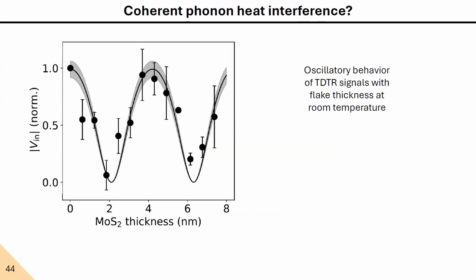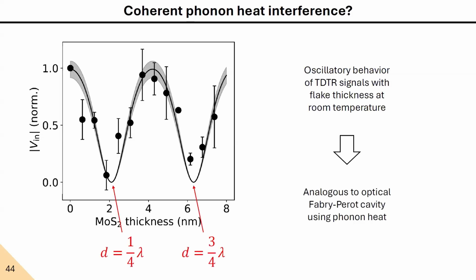If we plot the signal magnitude normalized to the substrate value for all our measurements, these are averages of multiple measurements and samples, so that we can cover the entire thickness range, we see this oscillatory behavior. And this is an experiment that is analogous to an optical Fabry-Perot cavity. But in this case, we're using phonon heat as our observable. And these specific resonances, where we see no signal, would correspond to 1/4 and 3/4 wavelengths of the phonons that carry heat.